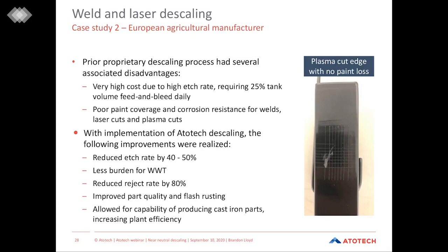If we look at the image on the right, this is a plasma cut edge that they normally had a lot of issues with. And so you can see with the evaluation done here that there's absolutely no paint loss from the crosshatch test. What you see with the gray area here is that they manually tried to remove some of the squares from the crosshatch area. This is just the scratching of the top layer of paint, so that's not actual paint removal. It's just scratching from trying to manually remove the paint from the crosshatch area.